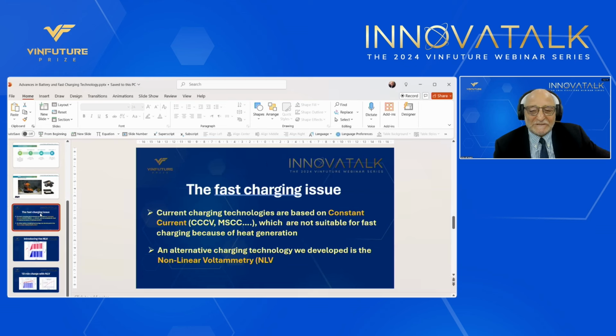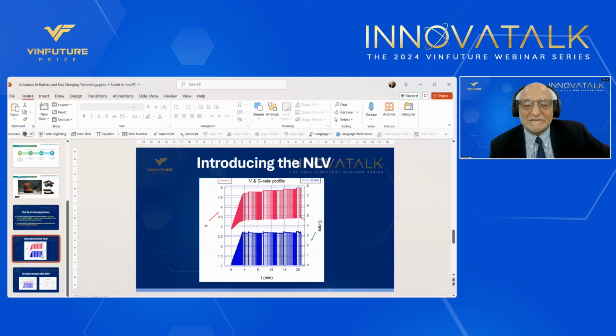Instead, we developed recently a new method based on so-called nonlinear voltammetry, NLV, which I would like to illustrate here very rapidly. So in the NLV, what we do is instead of controlling the current, we control the voltage. And we apply a series of voltage plateaus. Within each plateau, the current goes to zero. So this is what we call a rest. And so the red curve here is the voltage profile, and the blue is the current profile. And this is an illustration of fast charging in 20 minutes to fully charge a battery, which means that if we go from, say, 20 to 80% state of charge, it will be only 12 minutes.